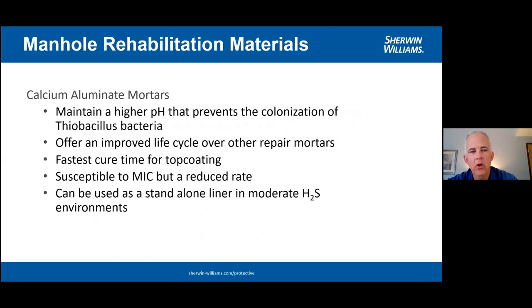Then we have calcium aluminate mortars. They maintain a higher pH than microsilicate mortars do. So what we generally do in the more aggressive structures, in the structures that have a lot of degradation or a real low pH going on, we'll look at doing recommendations of a microsilicate mortar and then an epoxy coating back over the top of it.